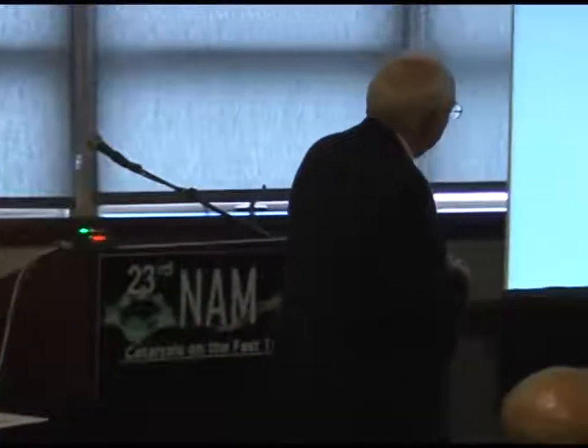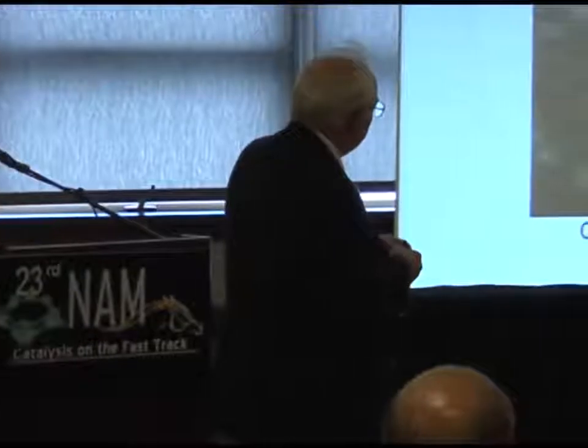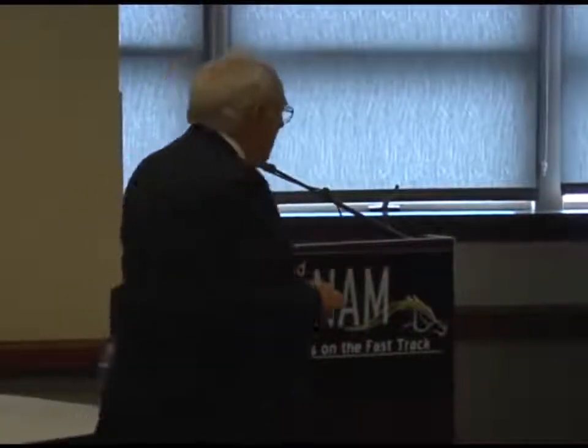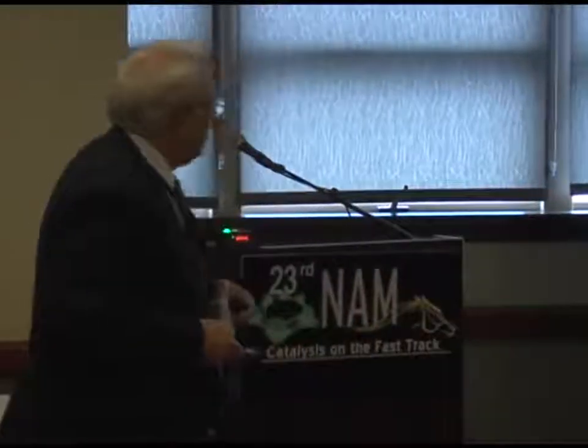In this case, one can also, with a good imagination, see the 6 atoms in the individual clusters, and we gave you a visual aid by showing them in the dots. These are no longer the octahedral arrangement of the Ir6(CO)16 because the electron beam has had an effect to scramble them a little bit.